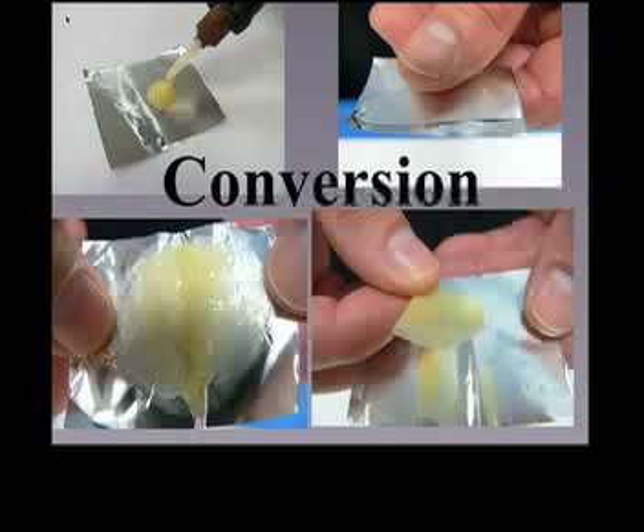A simple way to test this is get your dual cure cement, put a bit in tin foil and put it between your fingers, letting it cure for the specified amount of time. I think you'll find if you're not using something like Dual Link, you're going to find a huge disparity among your dual cure cements.